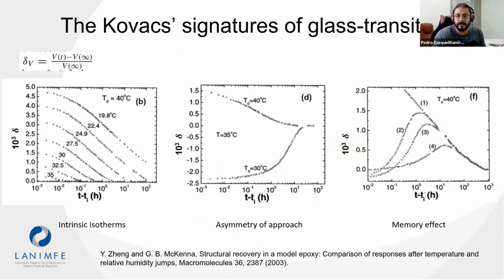Another of the glass transition's main features are the Kovacs signatures, which consist of a series of experiments where the structural recovery is probed. Such experiments help to characterize the relaxation processes suffered by the system toward the equilibrium state after thermal or mechanical perturbation. By direct measurement of the evolution of the volume, enthalpy, or other thermodynamic quantities through the variable delta, which is defined on the screen, several important features of the glass transition can be identified, namely the intrinsic isotherms, the asymmetry of approach, and the memory effect experiment.